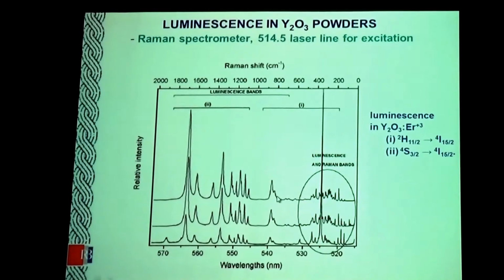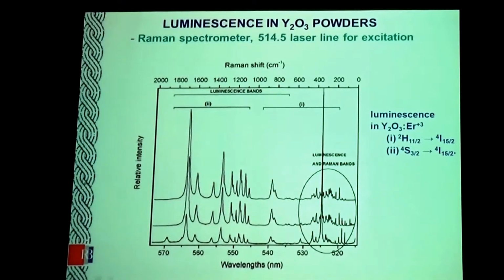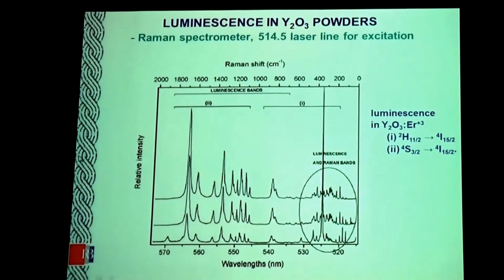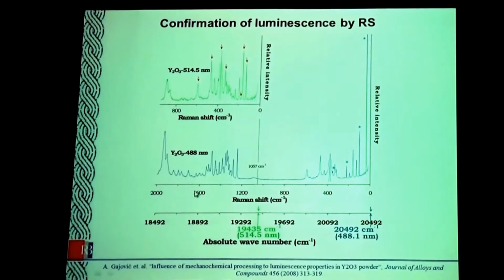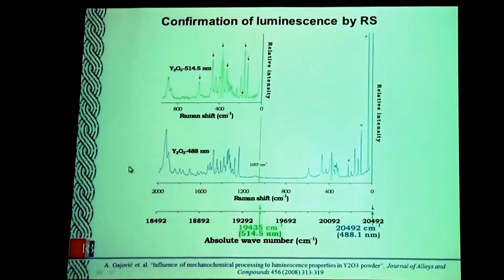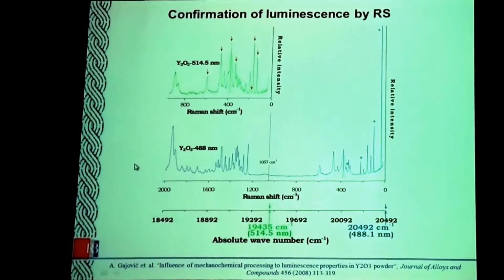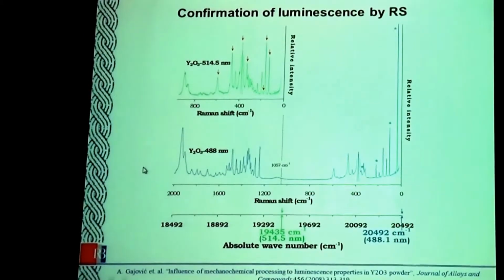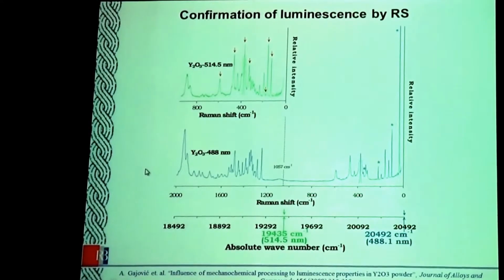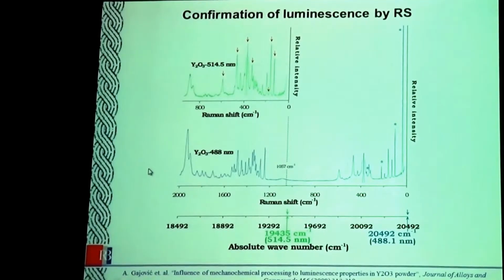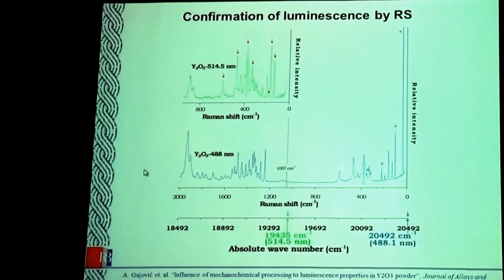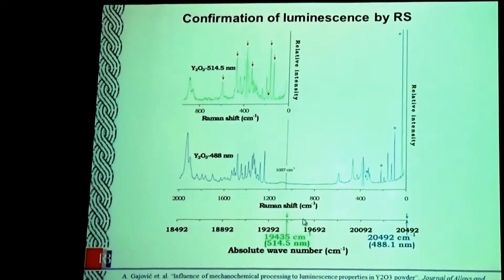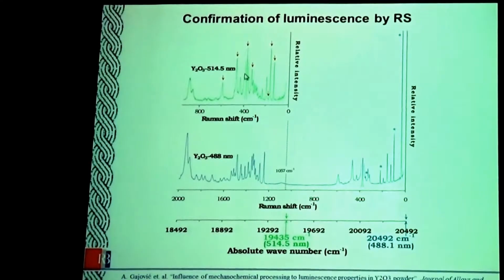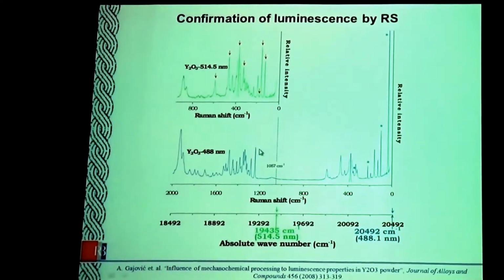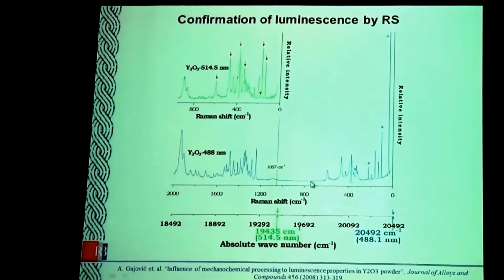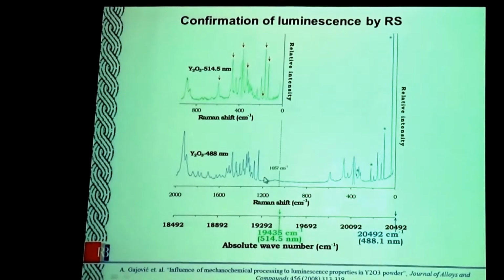But how do we know this is luminescence? Sometimes somebody can tell us, okay, but this could also be Raman bands, maybe you have something else. However, if we change the excitation line, as I mentioned, we always observe just the Raman shift. We have an excitation line, and we have a shift around the excitation line, and this shift, this band, is actually just part of the energy which the system grabs for vibration. While when you have electronic transition, electronic transition has fixed wavelengths. So if you shift your excitation, all Raman bands, which are mixed in this case with luminescence light, will be shifted. So this part is Raman active bands, and this is luminescence.